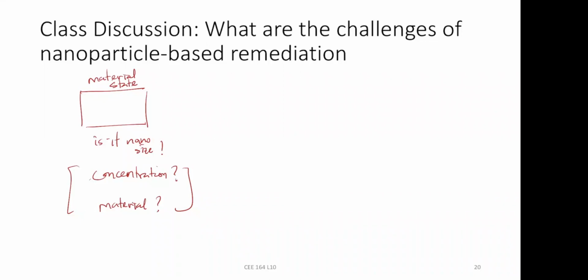Concentrations and size: smaller is better, but if they're too small, obviously they are going to react and aggregate faster. And why do I say why is it nano size? Well, we call it nanotechnology, so it has to be nano size, but that's not true. If you create nanoparticles, they don't stay as nanoparticles in the long term. The size is going to change. Nano size is going to aggregate. So if you have smaller particles, they are going to aggregate and become bigger. And once the size grows, it becomes like micron particles, so it's no longer nanoparticles. That means not only does its reactivity decrease, you cannot even inject them, because as your size increases, it's also difficult to inject. If you look at the transport of particulates,